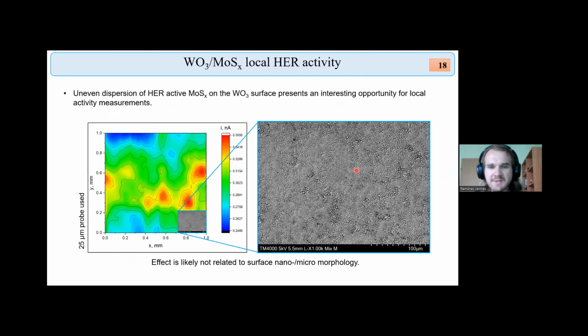And finally, these composites, because they have possibly uneven dispersion of molybdenum sulfide throughout the tungsten oxide matrix, are also a very interesting candidate for local hydrogen evolution reaction electrocatalytic activity measurements by scanning electrochemical microscopy. So these samples were investigated in much the same way as the previous ones, only here we assume that the tungsten oxide does not actually evolve hydrogen under these applied conditions, whereas molybdenum sulfide should. And here a slightly larger probe was used, and this map is 1 millimeter by 1 millimeter. We do find some hotspots in this heat map, which means that hydrogen evolution occurs more rapidly at these spots.